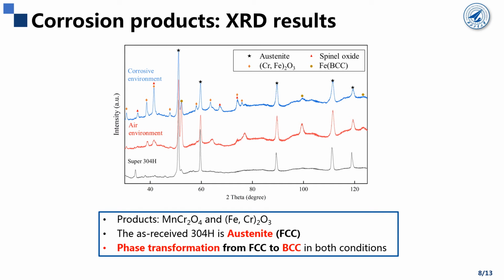In this page, we give the XRD patterns, which include the creep rupture specimens together with the raw material. Then we can find the surface products are mainly characterized as manganese chromium spinel oxide and chromium-rich oxide containing iron. The as-received 304 steel is austenite, that is FCC structure. However, after the creep fracture, we can find the existence of BCC iron structure, which means the phase transformation occurs from FCC to BCC structure in both testing conditions.